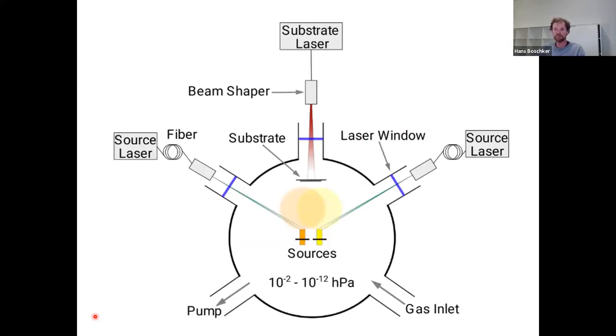This is thermal laser epitaxy. We have a very simple vacuum system with a substrate heated by a laser and elemental sources, each individually heated by a laser. These lasers are continuous wave. The only thing the lasers do is heat the target until evaporation starts. Because we use an individual laser for every target, we can tune the flux of every element simply by tuning laser power. Everything else is very simple, meaning we can still put background pressure into the system. In this talk I'm going to focus on the evaporation part of the metals.